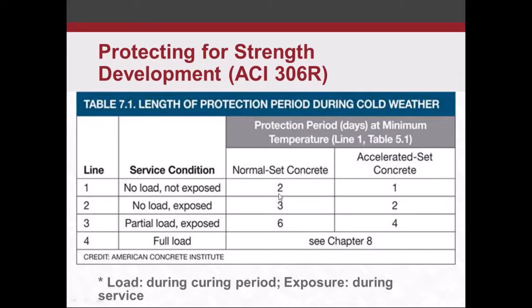Our protection period would only be 2 days. Again, we're going to be maintaining 55 degrees for 2 days. You've got accelerated set concrete, it's just 1 day. No load and exposed, we've got a 3-day protection period, or a 2-day protection period with accelerated set. Partial load and exposed, we've got a 6-day protection period, or 4 days for accelerated set concrete. Partial load exposed, that's certainly not uncommon during construction. No load and exposed is certainly not uncommon. So protection periods between 3 and 6 days are probably the most common.